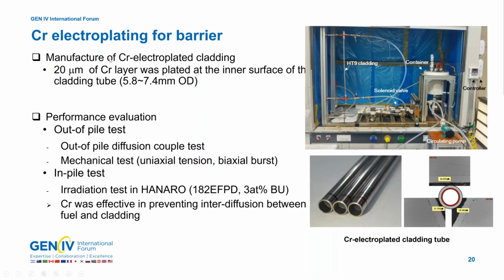So this is the chrome electroplating apparatus for electroplating of chromium on the inner surface of claddings. A layer about 20 micrometers thick was placed on the inner surface, and we did an out-of-pile test. Then we made a cladding and a fuel rod, and we did an irradiation test in Hanaro. I'll show later that it works well to prevent interdiffusion between fuel and cladding.